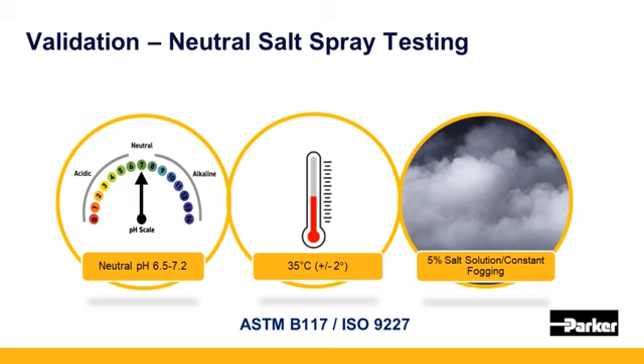Neutral salt spray test is one of the most common corrosion tests accepted in industry. There are a few equivalent standards that specify how it needs to be run. When setting up a neutral salt spray test, several critical parameters such as pH, temperature, salt solution, and pressure are set as constant. pH is neutral, as indicated by the name, and the 5% salt solution is constantly being atomized and making fog to supply into the chamber.